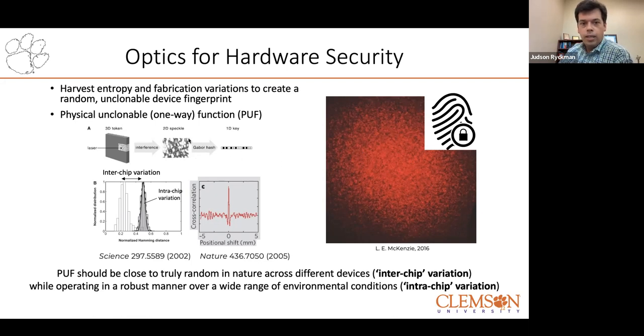You can then digitize it to make it more measurable, in that you could compare it before and after processing. And there are a few important traits here. Any two chips obviously should have a very different signature. So this is measured as an interchip distance, something that's called the Hamming distance. So if you digitize to ones and zeros, you can compare two different keys, for example, to see how similar they are. If they're fully uncorrelated, the Hamming distance will be 0.5. And if they're exactly the same, the Hamming distance will be 0. Of course, you allow for some bit errors. So ideally authentic devices have a small Hamming distance, and non-authentic devices have a Hamming distance near 0.5.